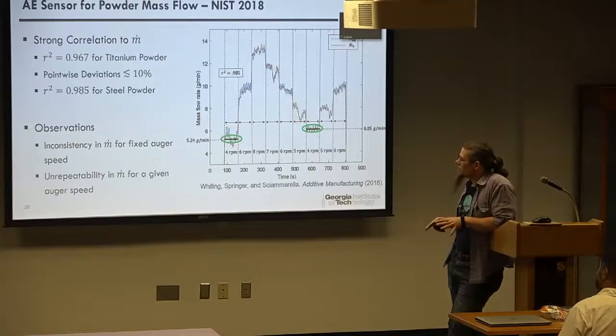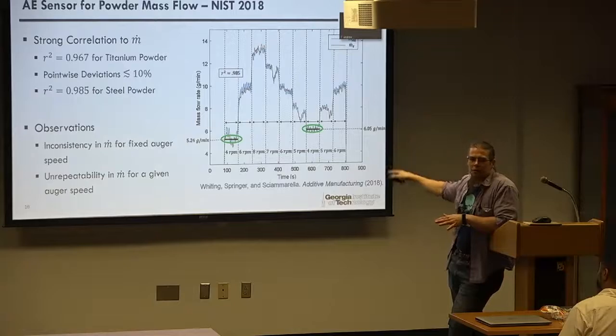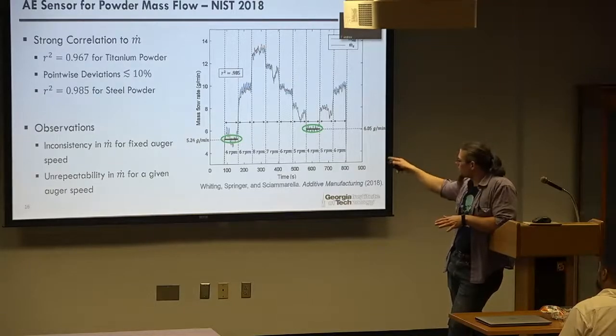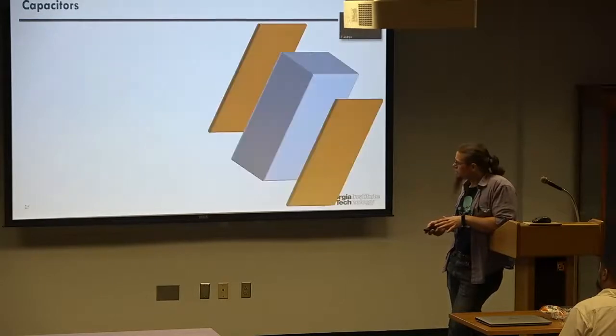We also have unrepeatability for the mass flow for a given Auger speed. That's demonstrated here between the 2 green. It's the exact same setting at 2 different times, and they're giving 2 different average mass flow outputs, right? Which is on the order of about 10 to 12% difference here in those mass flow outputs.